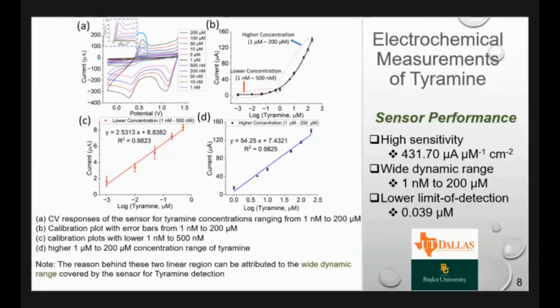As I said, it is a pretty wide sensing range. We prepared solutions all the way from 1 nanomole to 200 micromole, and we could see two distinctive ranges right here. So we just divided this into two: from 1 nanomole to 500 nanomole, the lower concentration, and 1 micromole to 200 micromole, the higher concentration region. And we got this plot to get the sensitivity. This is raw data for all these different concentrations of cyclic voltammetry, and we got the plotted data for sensitivity.